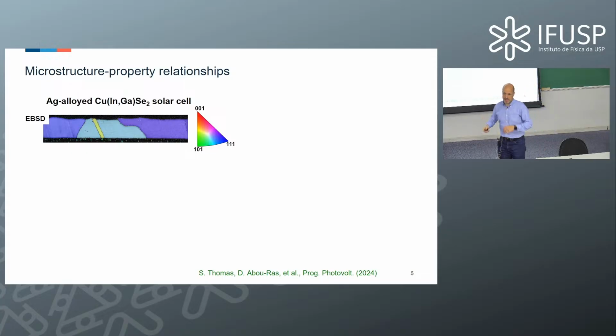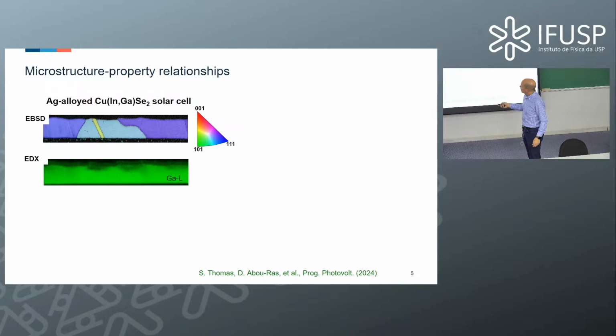In this case, you have the impression, oh, this material is quite nice in terms of grain size, so it should be a good material, yes? I mean, it looks nice already from the grain size. But if you look at the elemental distribution, there's indium and gallium, you can see that there is a depletion of gallium at the top of the layer. So what seems to be homogeneous is not so homogeneous anymore.